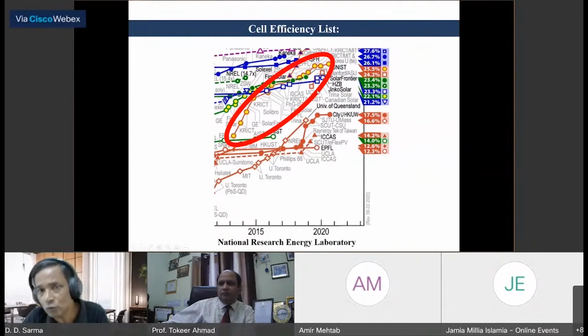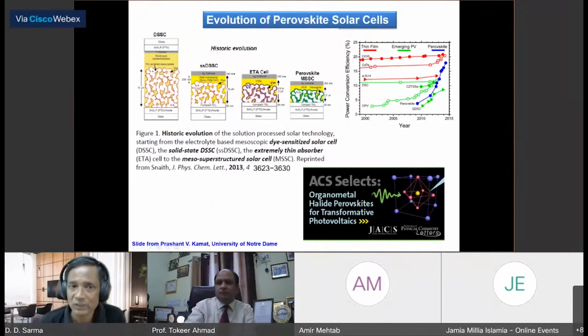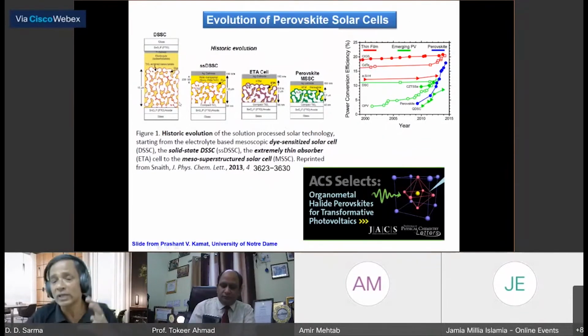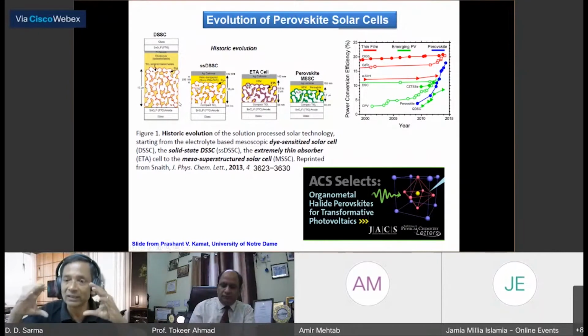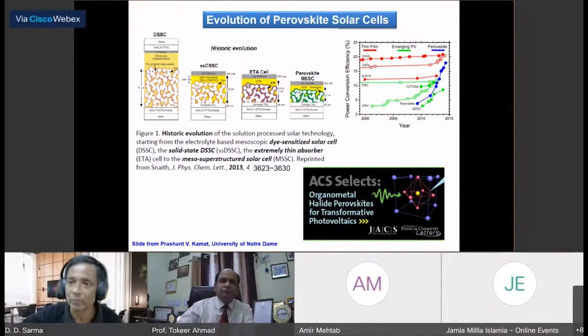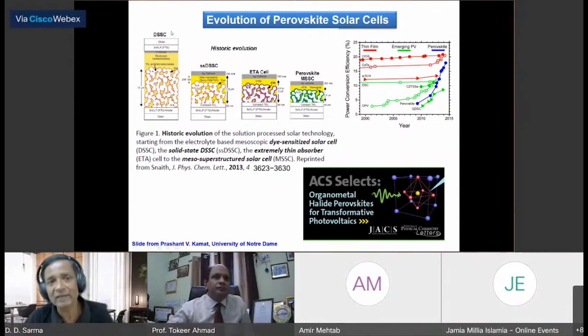Only efficiency is good. Actually, it's much more than efficiency. All the time we want to make the solar cells thinner and thinner so that the weight is less, so that we can mount them everywhere. But in order to make it thin, it must absorb very efficiently. And that gave rise to new technologies called dye-sensitized solar cell, where with a 10 micron thick active layer, you can make the solar cell.